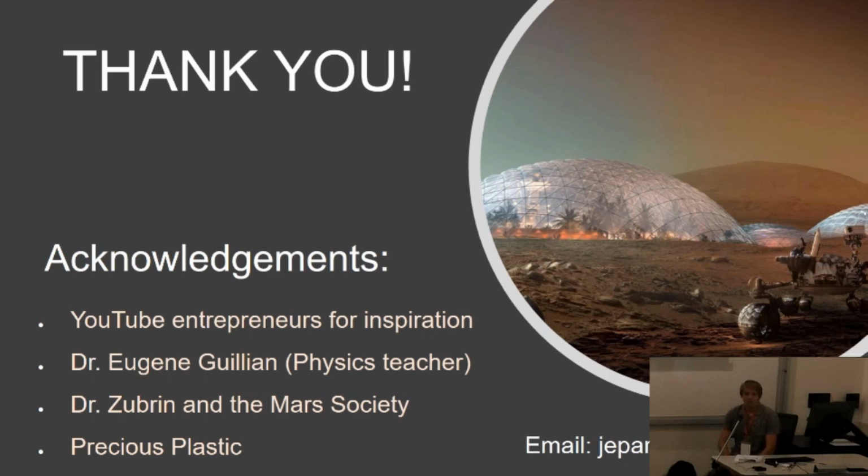I forget if you mentioned what the ratio of the regolith sand to the plastic was, let's say weight for weight. Did you even vary that? All of the samples were 60 grams by weight, and I did 25% plastic to 75% regolith, as well as 75% plastic to 25% regolith, as well as a 50-50 mixture for all of the plastics individually. With all of those, I also did a mix of multiple plastics, so it would be like 12.5% polyethylene, 12.5% polypropylene, 75% regolith. I tried to cover my bases for that. By weight, you mixed them 50-50 by weight? Yes, by weight.